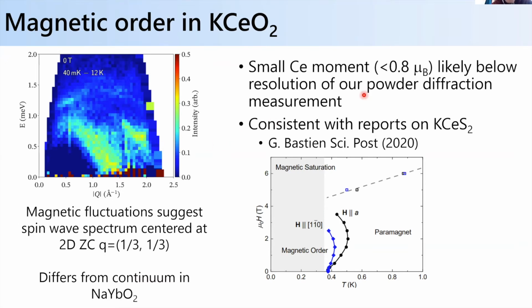And it's also consistent with recent reports on potassium cerium sulfide, which is the sulfur analog of this system, where again, via muons, they actually see the onset of magnetic order at low temperature, at around the same temperatures. Okay, so in this case, the cerium analog seems to be a bit more boring.